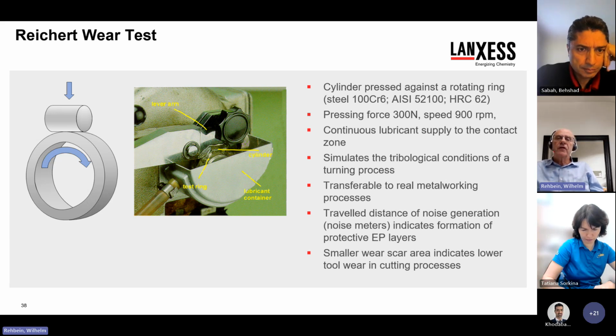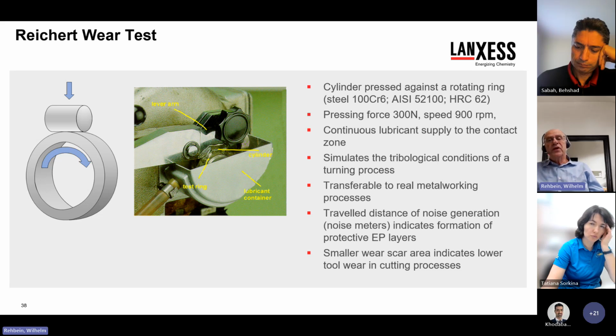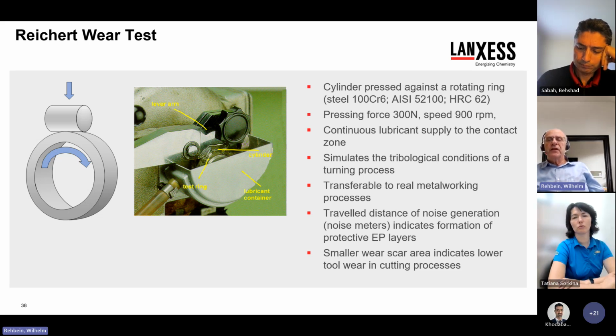For the evaluation of the performance of metalworking fluid emulsions, we used the so-called Reichert wear test. In this test, a steel cylinder is pressed against a rotating steel ring with a pressing force of 300 Newton. And during the test, the ring rotates in a container that is filled with a metalworking fluid emulsion. So there is a continuous supply of metalworking fluid to the contact zone. We can say this test simulates the tribological conditions of a turning process.